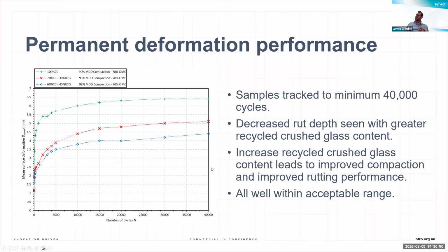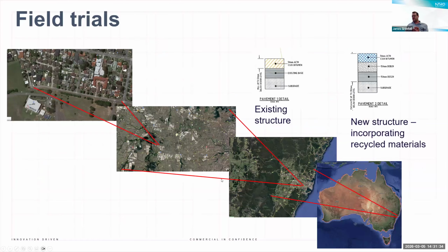And obviously there's also that additional aspect that we've now mechanically stabilized with a recycled crushed glass material to get better performance. So you can start to see we're going to get some sustainability benefits by doing that. We then took that to a field trial. One of the things is we did see that adding even more glass actually improved the performance. We did some calculations to understand how much available waste glass there was, and determined that probably going to 40% might be too much, and to undertake a few projects there might not be enough available recycled crushed glass after quite a small period of time.